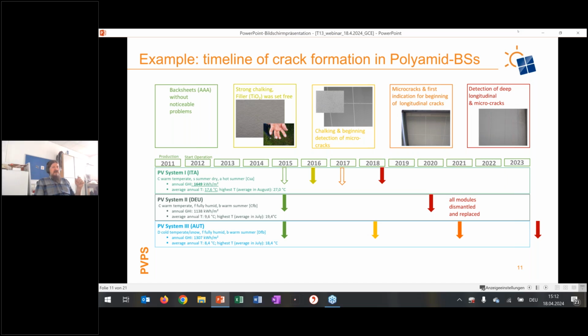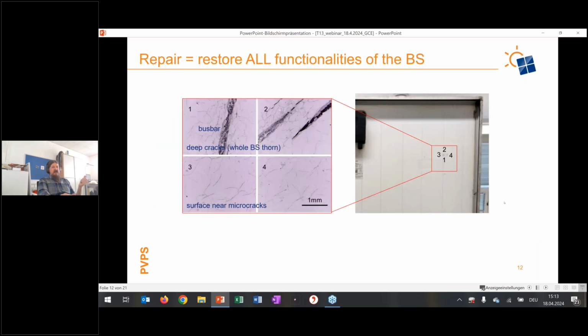In the next step, you saw small micro cracks forming on the surface that over time grow into really deep cracks, in most cases above the bus bars, where we have additional stresses. And in the end, these cracks go through the whole backsheet, exposing the module interior. You can see that in hot climate zones with more severe climatic conditions, it happens much faster than, for example, in an alpine climate like we have in Austria.